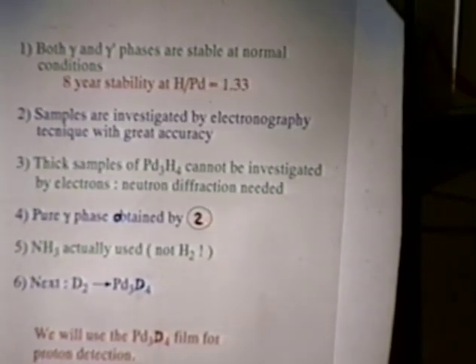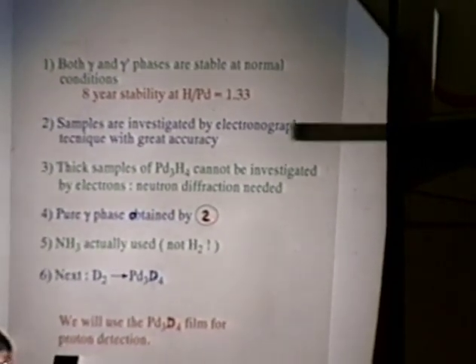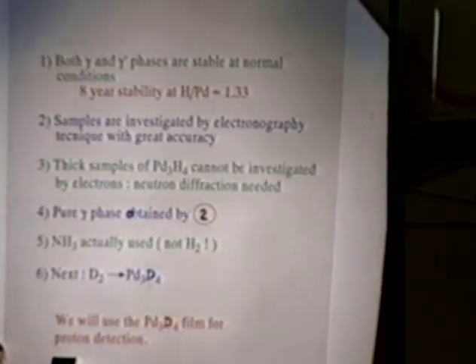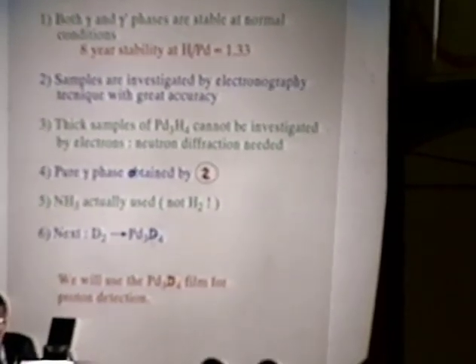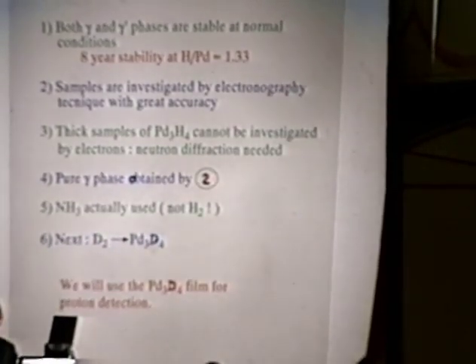Unfortunately, this is not possible for thick samples. This is possible only for very thin ones, 100 angstrom only. Otherwise, you need neutron diffraction, and this has not been done yet. And also, thick samples have not been produced. With the second procedure, pure gamma phase has been obtained. Actually, not exactly hydrogen was used, but ammonia.